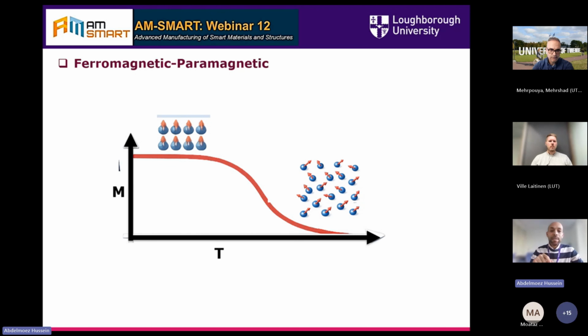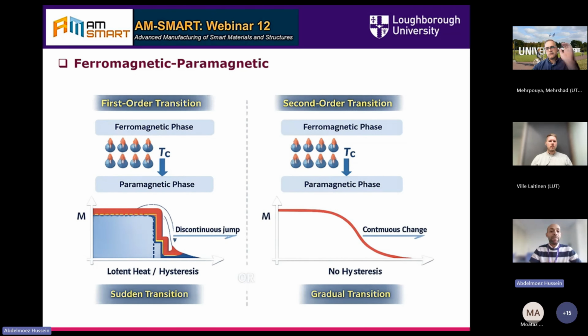Here we can see the spins of the magnetic domains are aligned at low temperature in the ferromagnetic state, and with increasing temperature they start to get randomized into the paramagnetic state. How can this process be affected? This transition is a very critical transition for the applications that we are looking for. There are two kinds associated with this transition. It could be a first order or second order transition.